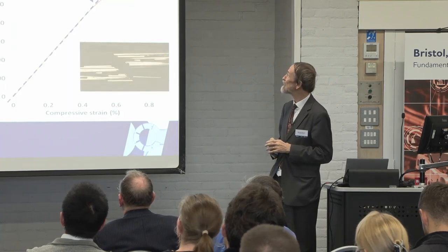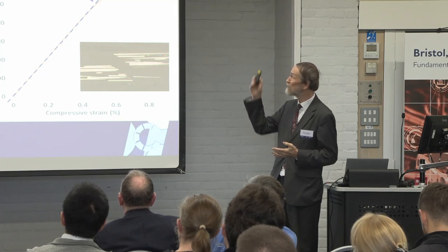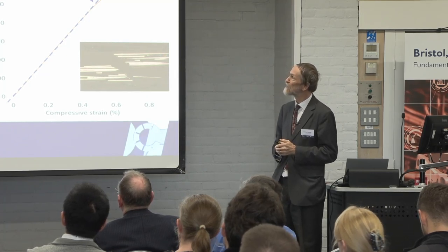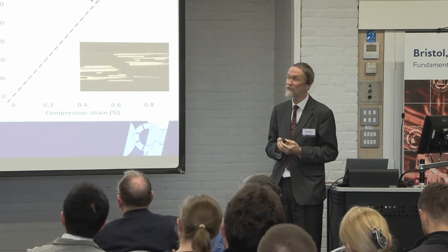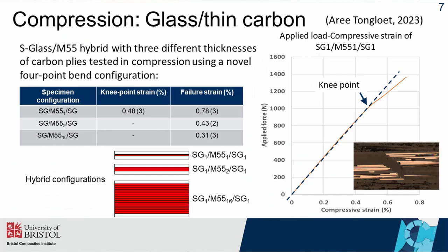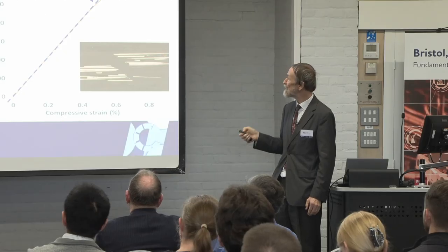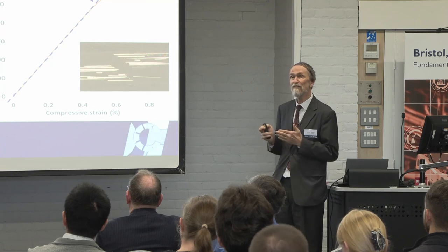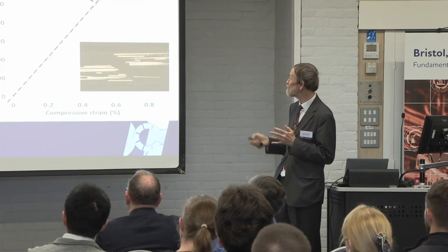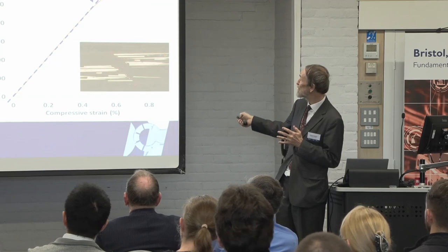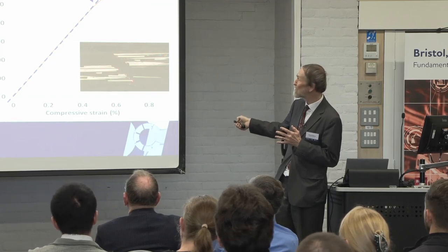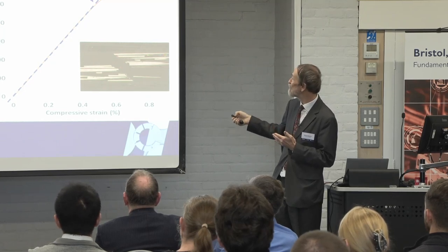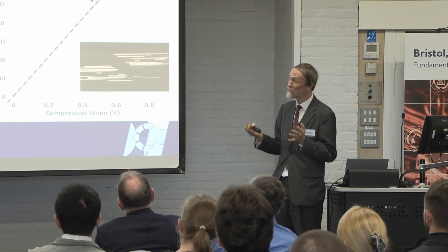We've also looked at compression in some recent work which our PhD student Aree Tongloet has been doing, combining S-glass and M55 high modulus carbon fibres. By looking at different combinations, different thicknesses of this M55, this is a thick orientation with a lot of M55. Here we've got two and one thin plies of that material. What we see is that if we have the thin plies, we can get a similar fragmentation behavior in compression in these materials. You see we have a fragment form there, but the glass plies are still intact. So these multiple fragmentations produce a knee point and some nonlinearity in the stress strain response, similar to what we saw in tension.